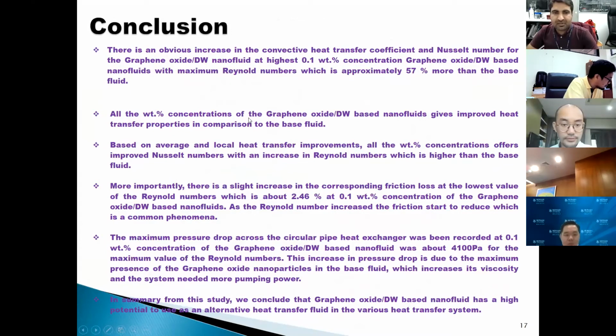All the weight percent concentrations of the graphene oxide distilled water give improved heat transfer properties in comparison to the base fluid. Based on average and local heat transfer improvement, all the weight percent concentrations offer improved Nusselt numbers with an increase in Reynolds number. Similarly, most importantly, there is a slight increase in the corresponding friction loss at the lowest value of the Reynolds number, which is about 2.46% at 0.1 wt.% concentration. The maximum pressure drop across the circular pipe heat exchanger was recorded at 0.1 weight percent concentration. So finally, in summary, from this study, we conclude that graphene oxide distilled water-based nanofluid has a high potential to be used as an alternative heat transfer fluid in various heat transfer systems.